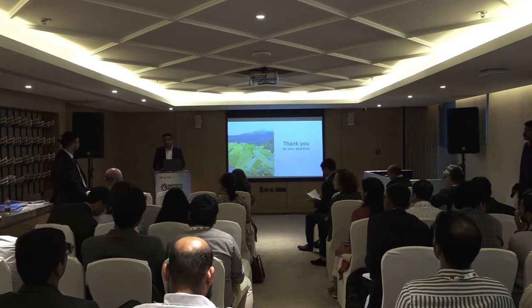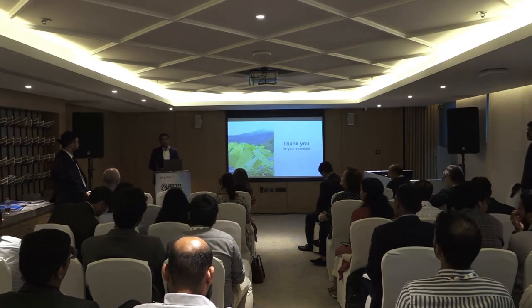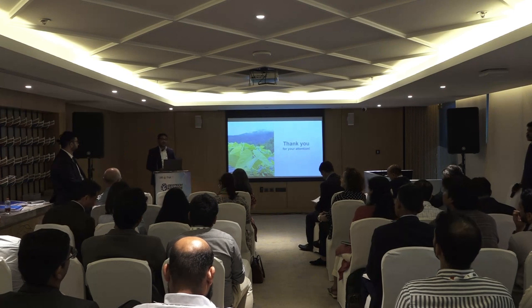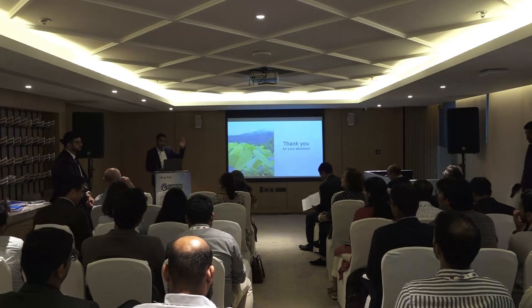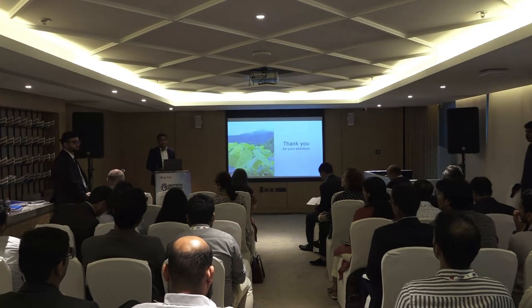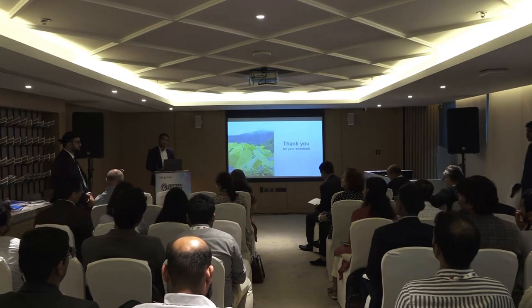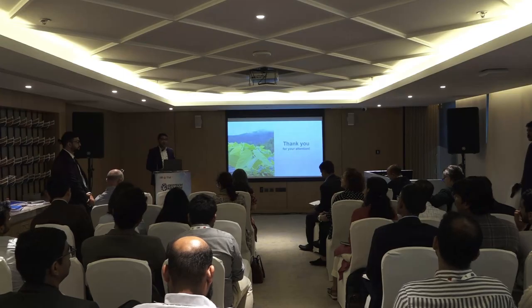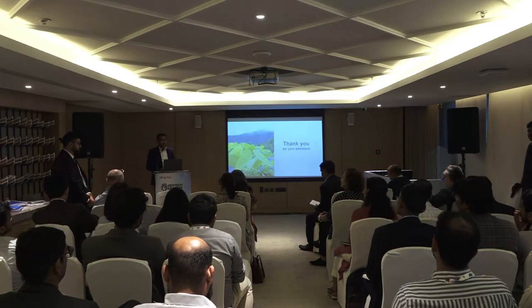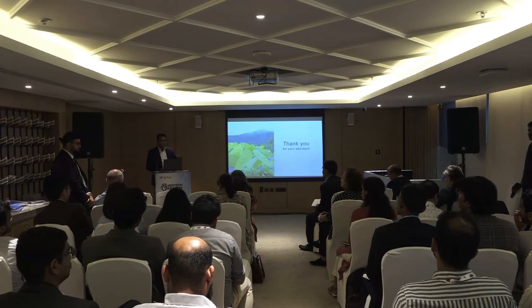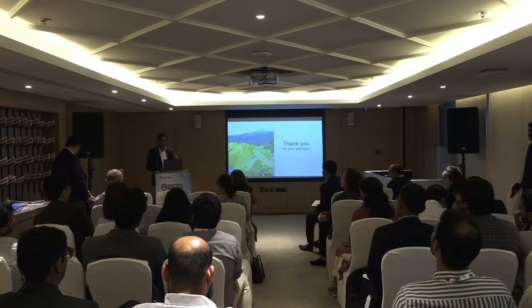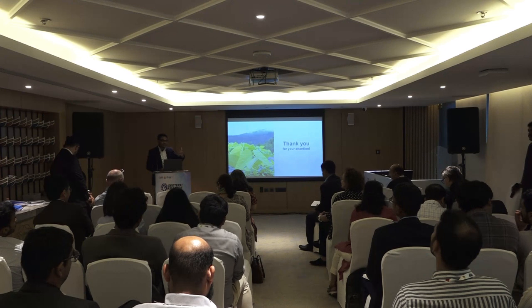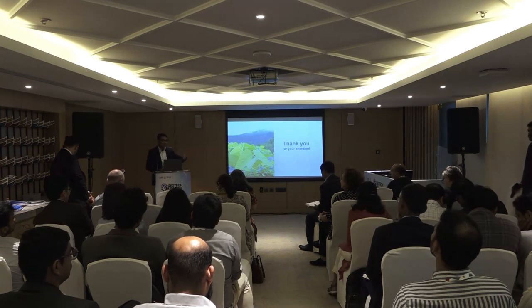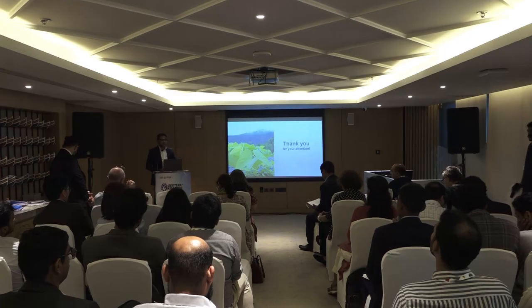Thank you very much. So, as I was mentioning, we were following the Indonesian standard, the standard that they follow in Indonesia, and for the reinforcement, for the steepness of the slope. So we have a slope which is more than 60 degrees. The tensile strength requirement was satisfied by the steel wire mesh, and that's what was also commonly used for Indonesia as an approach. They tried also other method, hydroseeding. They tried also using geotextile as a base for the growth along with hydroseeding, but it was not performing.